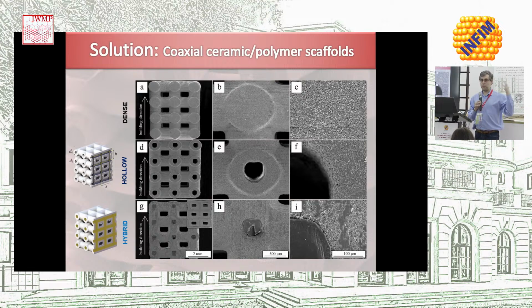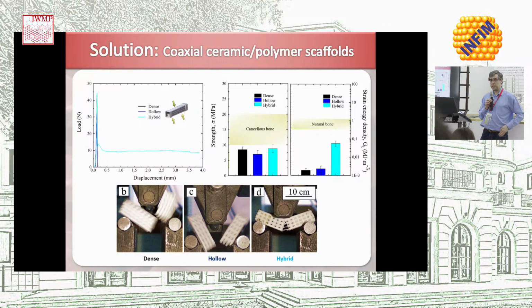Okay, because in the woodpile structure you have polymeric fibers only in 2 directions of space, while in this structure you have them interconnected in the 3 dimensions, so it doesn't matter how you load it, you're always going to find polymer opposing any crack bridging and any crack propagation through the structure. So this is a better option in terms of having isotropic reinforcement of the material. And a real good reinforcement in terms of toughening of the material is achieved, even in bending, under bending stresses.